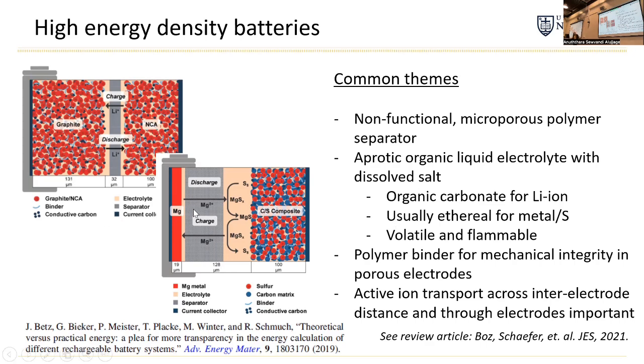And then polymers are also used in these cells, as I mentioned, as the binder. And they're very important in our commercial designs for maintaining mechanical integrity, right? So as intercalation and de-intercalation happens, as the lithium goes in and out of the particles, there can be volume changes. And so the binder is important for holding all the parts together, so we ensure electron transport, so the porous layer here does not get disconnected from the current collector, and so that none of the particles are disconnected from the carbon.